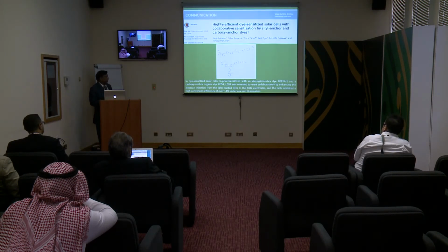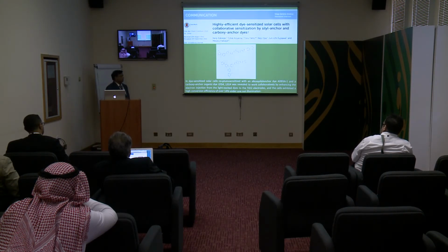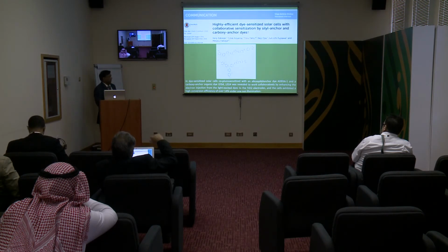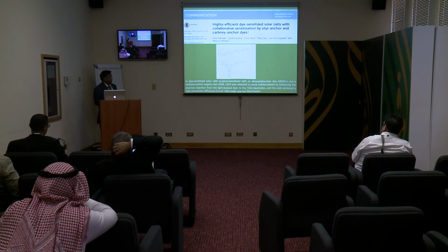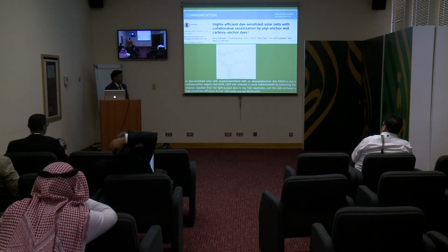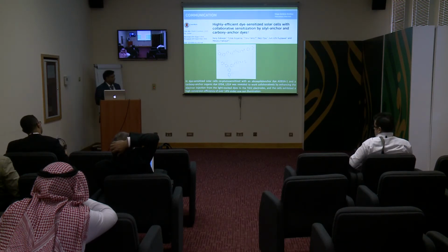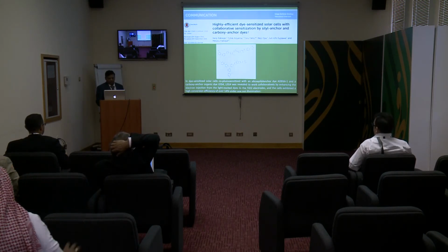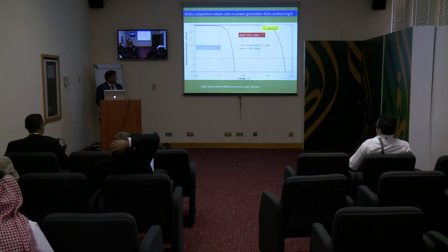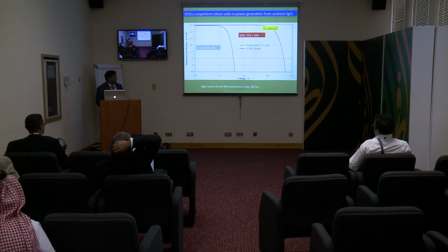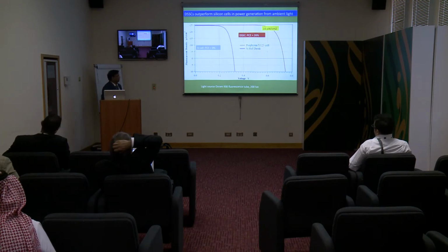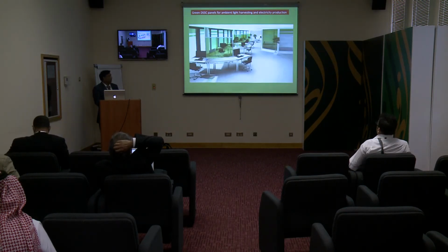This is another combination of co-sensitization they obtained, using mainly trimethylsilyl as an anchoring group, which increases the binding constant and also reduces the recombination to get high performance, in combination with the dye. They reached over 14% efficiency. And this is just a comparison at low light intensity, showing how the DSC supersedes silicon cells.